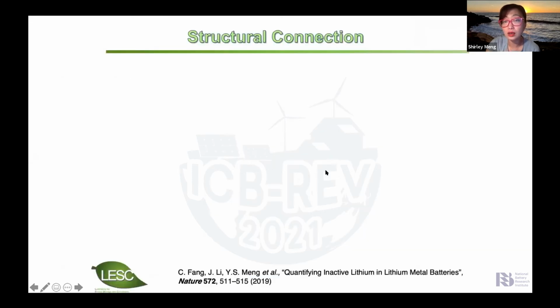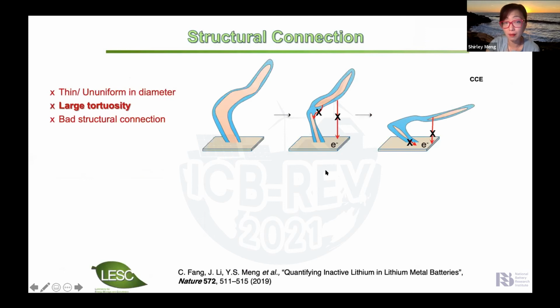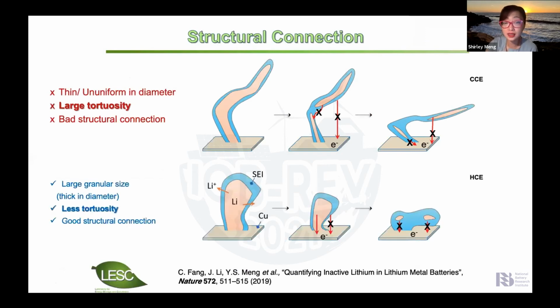But in our study, we have a different hypothesis. So the hypothesis is that because of the microstructure difference, so we are using some cartoon picture to demonstrate our hypothesis. If you have this kind of thin, high aspect ratio, tortuous microstructure, when you deposit the lithium, the difference may not be that big because, this is long and thin, this is short and fat. You can see the same amount of lithium.